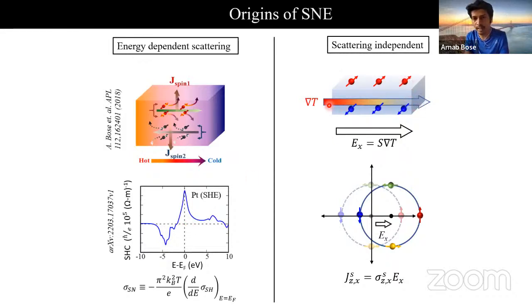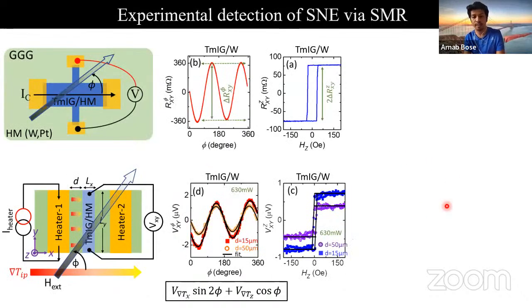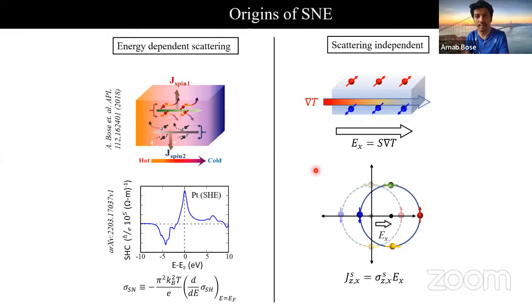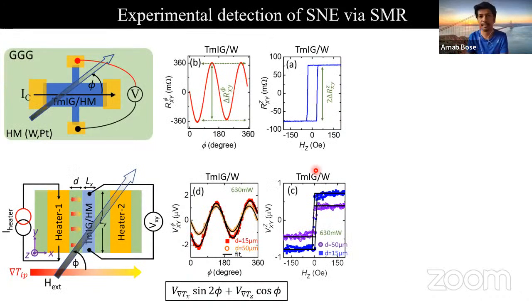And the second mechanism is that when we apply the thermal gradient, we get a local electric field due to the Seebeck effect. That electric field also brings the system into non-equilibrium, shifting the Fermi spheres. And that could naturally lead to the generation of transverse spin current without any scattering mechanism. That means for this mechanism, if we have a material that has a high spin Hall effect and a large charge Seebeck coefficient, then we can also have a very large transverse spin current. Towards the end of this talk, I hope to convince you which of these mechanisms is the dominant contributor.